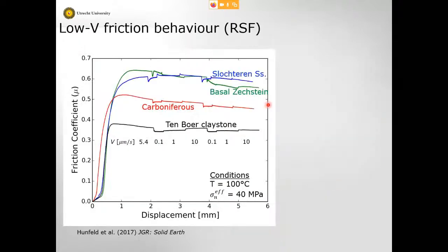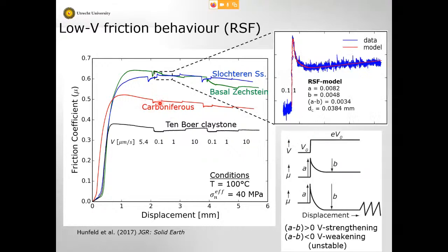Here's some typical results from Luc Hunfeld's PhD, friction coefficient against displacement for these different lithologies. Blue, the reservoir sandstone. Green is this anhydrite carbonate at the base of the evaporites. And the Ten Boer claystone, that's the claystone on top of the sandstone, and here's the substrate, the Carboniferous. And by changing the velocity that we impose to measure the friction coefficient, we can see how sensitive the strength is to the velocity using this classical rate and state friction approach to quantify the rate dependence of friction. That's what Luc did for all of these different lithologies and for all kinds of mixtures.